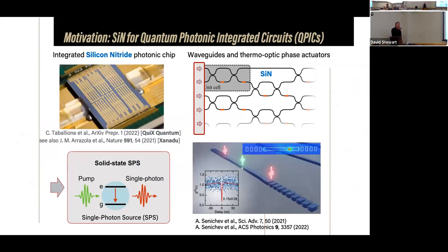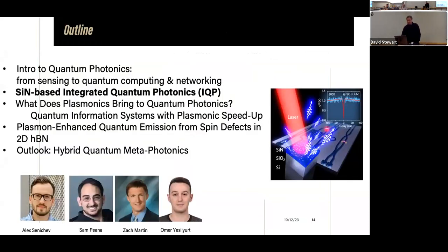So we have this material platform, we have existing foundry. We basically could make millions of different elements. What is missing is single-photon sources, and that's exactly why we were so excited when we first observed these sources in silicon nitride by slightly modifying the standard procedure to make this material, and then doing all these efforts to integrate these sources with circuitry, and that's what I'm gonna talk about.